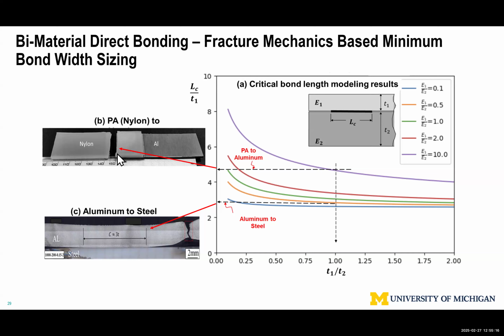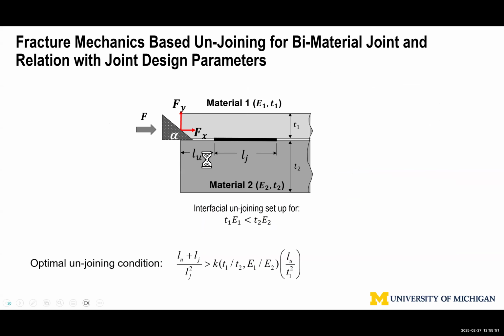So if you look at the battery, recently I also looked at battery packs when you drive an electric vehicle, they put a massive amount of adhesive everywhere, right? Because they are not sure how much is needed. So what we are saying is, you have a minimum bonding length, taking into account some of the defects, some quality issues, add say 10%. That's all you need to take on the worst case scenario load. Anything more than that adds cost, adds inconvenience. Right? And then we can design a process. For example, this length is important. If it's too long, you're not going to open up effectively. It has to be sufficiently short. This is based on fracture mechanics principles, and so we can pop it open.